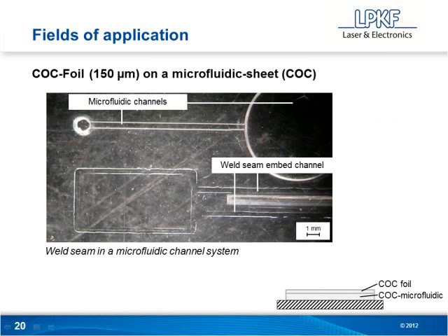COC foil, like I mentioned, these are gaining a lot of traction. 150 micron thickness, and this is actually a microfluidic sheet, which opens up another realm of possibilities for microfluidics. Essentially what's happened here is the lower sheet, the COC, you can see down here has channels basically etched into it, and then the COC foil is laid on top of it.